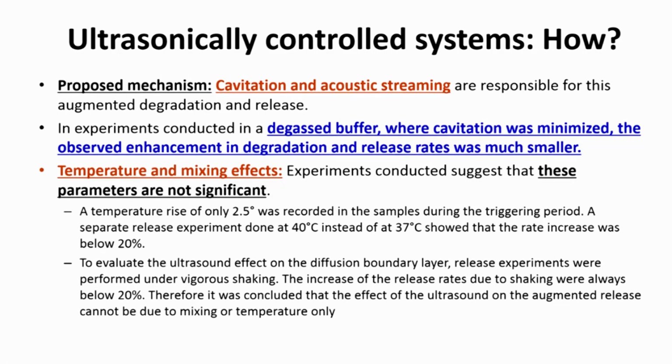Obviously there are also some temperature and mixing effects that can happen, but when the experiments were conducted, they found that the temperature increase was not very significant. The temperature rose only by 2.5 degrees during the triggering period, and it was shown that there is not much change in the release rate at different temperatures. Similarly, the ultrasound effect on the diffusion boundary layer was examined, and the release experiment was performed with vigorous shaking, and again it was found not to be very significant. So it is basically cavitation and acoustic streaming that cause the system to work.